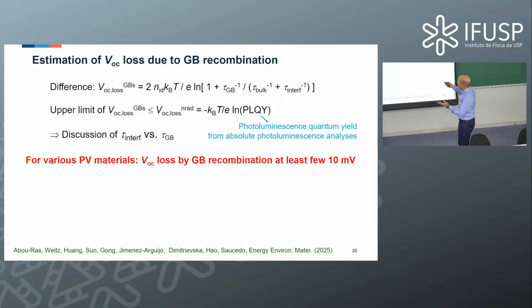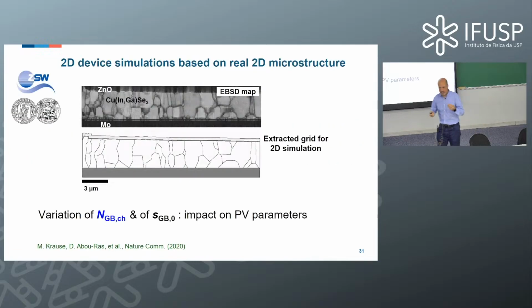Of course, it's good to do this in this way, and it's a nice way actually to calculate, but we have, of course, tools to really simulate the device performance, and this is actually two-dimensional device simulations that we can use, for example, using Sentaurus software. And what the colleagues in the University of Halle in Germany did, they took a grain boundary grid extracted from an EBSD map as a basis for the calculation of the device simulation. And this is quite nice because then you can really use the real microstructure as a basis, and not just some arbitrary grid that you can think about. It's a real grain boundary grid that is extracted from an EBSD map.